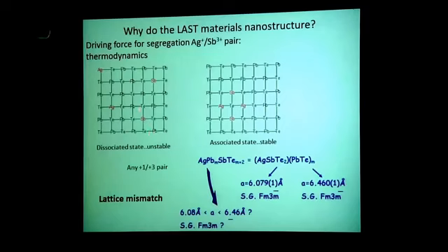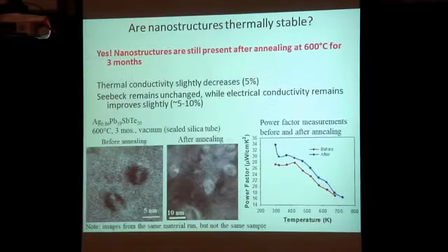Another driving force could be the fact that a 1+ and 3+ pair for silver and antimony cannot really disperse very well because it's attracted in a sublattice of 2 pluses. It's like having a sublattice of 0 and having a +1 here and a -1 there. So they are attracted. As these things cool from the melt, to make a local average of 2+, silver and antimony have to find each other locally nearby. So this is a nucleus of a second phase, and then it could grow. So there is a thermodynamic driving force, it appears, for these things to phase separate.